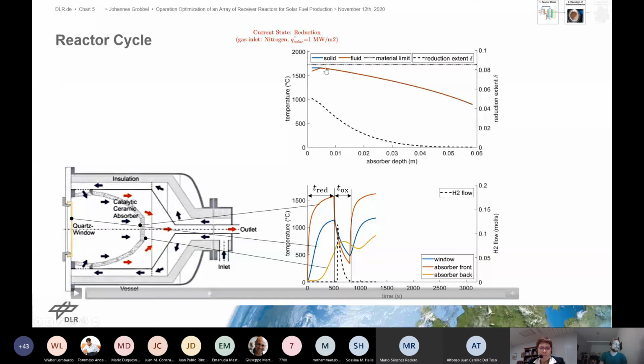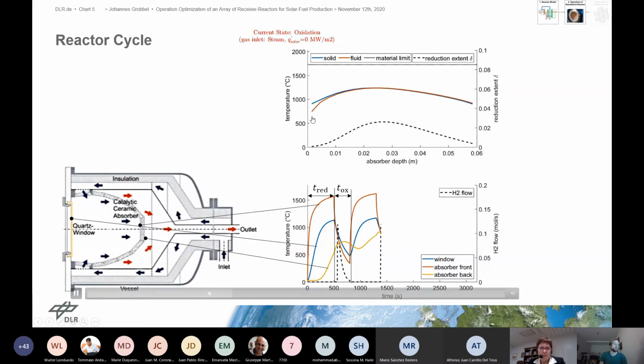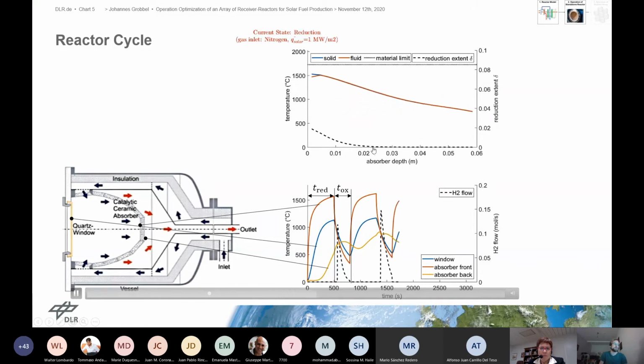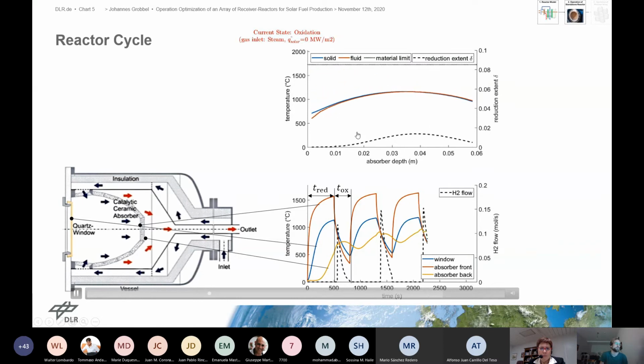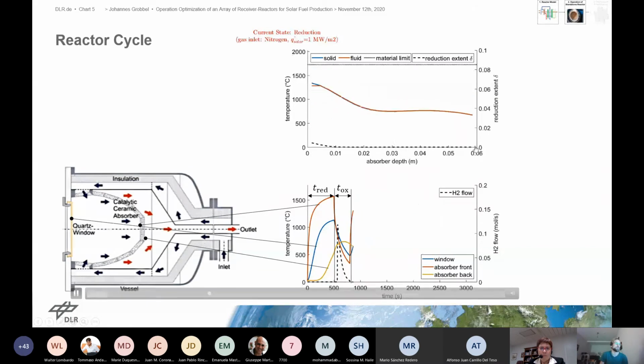Now, when we switch off the radiation and switch on the steam flow, we can see an interesting phenomenon. We see the temperature drops in the front and the reduction extent as well. But we also see that the reduction extent in the back suddenly increases. In fact, the hydrogen produced here in the front acts as a reducing agent and reduces parts of the absorber which were not reduced before here in the back. And you only see a peak of hydrogen at the outlet, marked as a dashed line, when the reduction extent at the exit or at the back of the absorber is greater than 0.